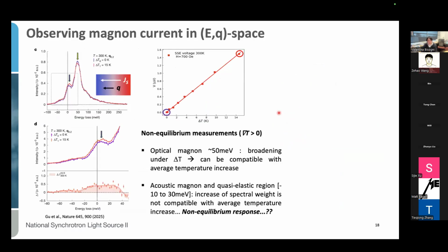Next, let's see what happens when we start to be in non-equilibrium. We activate our device and generate a thermal gradient of around 15 Kelvin at 300 Kelvin. And now we measure our RIXS spectrum again. Here you can find the purple spectrum, which is our equilibrium measurement, as I just discussed in the previous slide. And in red is the RIXS spectrum measured in the presence of magnon current. Let me also specify that the magnon current and the momentum relationship for this spectrum is as illustrated here, such that the momentum transfer is parallel to the magnon current for this measurement.